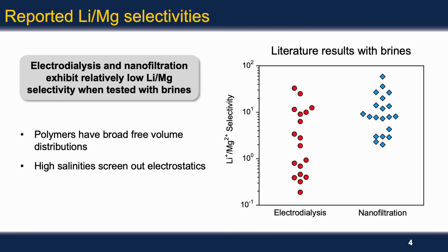If we look at the literature-reported lithium-magnesium selectivity values for electrodialysis and nanofiltration membranes that are tested with either real brines or model brine solutions, we'll find that most of these selectivities are actually relatively modest or low. The issue with these conventional approaches is that polymer membranes tend to have very broad free volume distributions, and so the principle of size exclusion is not very effective with these types of materials. And furthermore, when you do these experiments with real brines, the extremely high salinities of these brines can screen out the electrostatics, thereby diminishing the charge exclusion principle as well.